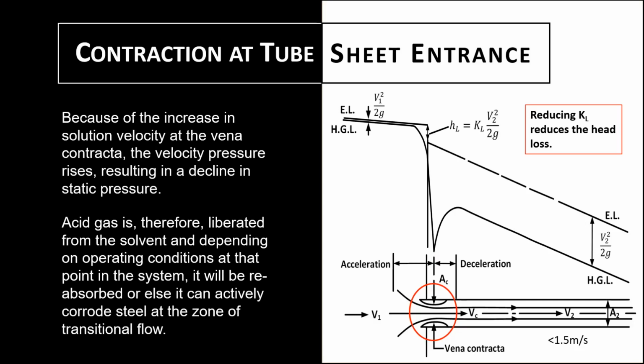Now note that there is a small permanent head loss, but also a rather large temporary static pressure loss caused by that vena contracta. At the vena contracta, which is the necking down of the fluid stream at the entrance, the static pressure can drop so low as to reach a point where the pressure is below the equilibrium pressure of the acid gas in solution, resulting in breakout of acid gas in the dead zone around that vena contracta. This acid gas then migrates along the tube wall until it reaches a transition zone where conditions are conducive to corrosive activity.